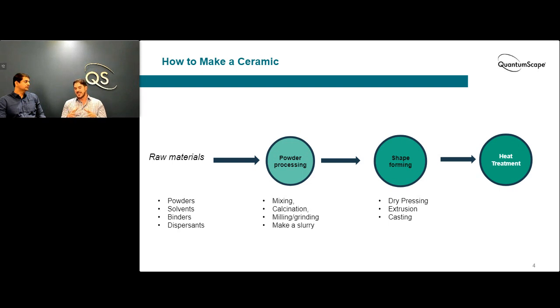Once you have your powder, that needs to be transformed into some shape. So whatever shape your final product needs to be, you've got to transform your powders into that shape. Sometimes that's simple, like pouring a powder into a die and then pressing it at high pressure to form a dense powder compact. Sometimes you can take the powder and suspend it in a liquid, often water, sometimes a solvent. Now that you have this suspended powder, which we call a slurry, you can fill that into a mold, you can extrude that into a tube, or you can cast it into a sheet with a technology called tape casting. But in all these cases, you end up with basically a powdered compact of material, which is not a ceramic yet. This is what we call the green body. It's the precursor to the ceramic.